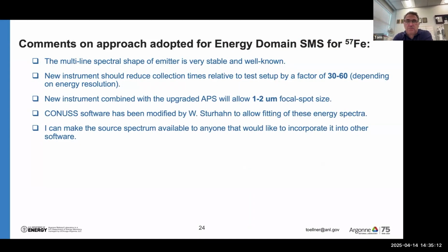So some comments on this approach. The multi-line spectral shape of the emitter is very stable. We're able to characterize it independently, and we know it very well. I've shown it's stable over hours, but in reality, it's forward scattering from an iron foil, and the iron foil will be capped with gold and in a UHV chamber, or at least a high vacuum chamber, and so it should be quite stable. It's also not sensitive to temperature significantly, or angle, or various things. So it should be very robust.